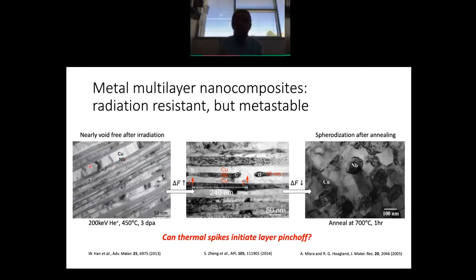And if you were to anneal this kind of composite at very high temperature, you would eventually get it to spheroidize, right? So all the internal layered microstructure would break down, all the particles would become much coarser, and the interface area per unit volume would go down. And as a result of that, the attractive radiation resistant properties of this material would be lost. Okay, so this thing is unfortunately metastable. It's not thermodynamically stable. On the other hand, it's also not unstable, right? So why is it metastable and not unstable?